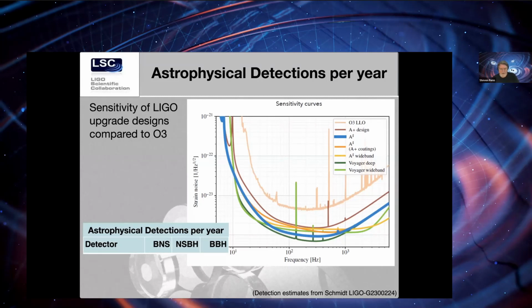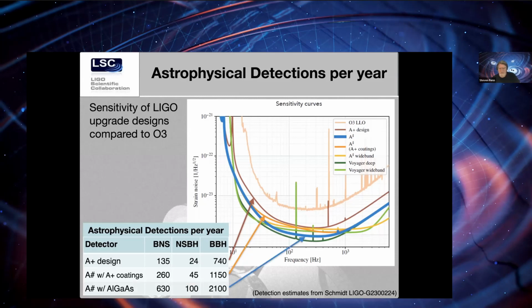So if you're looking at the noise curve that's plotted there, if we hopefully get to the A+ design, it should have this sensitivity shown in this reddish brown color. As you switch to A#, in the post-O5 committee report, they investigate A# and they choose to still use the A+ coatings. And if you do that, you do get an improvement mostly from larger test masses and the increased laser power and increased squeezing. But if you add on to that now a switch to AlGaAs coatings, you double that detection rate. It's sort of average doubling over the 3 different sources just by switching to AlGaAs coatings. And this, I'll point out, is still using the upper limit. These detection rates are probably much better.